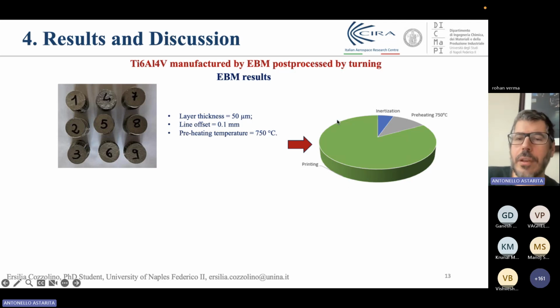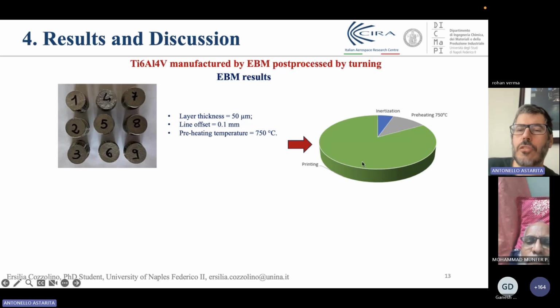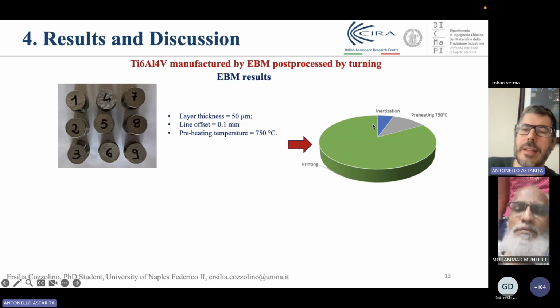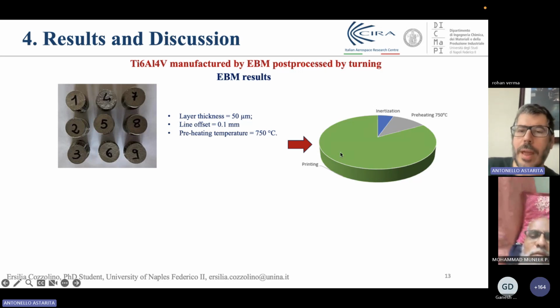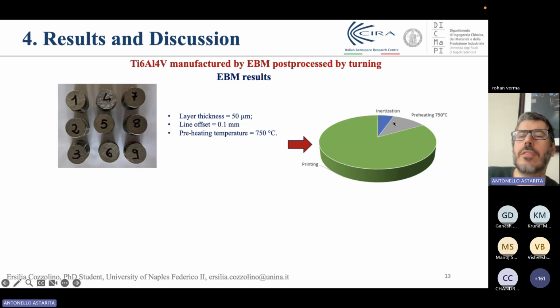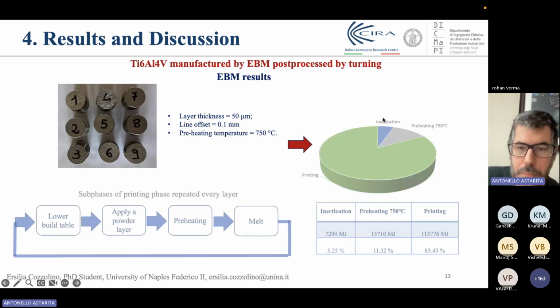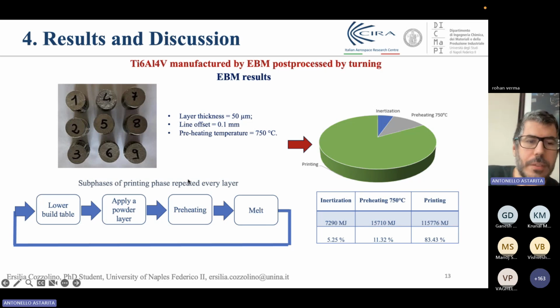In this pie chart, you can see the use of energy for the different stages of the process. You can see that most of the energy, of course, is required for the printing, but you have a non-negligible part of energy that is due to the preheating of the whole job, and another non-negligible part that is related to inertization. Okay. So this is, let me say, the flow chart of the process, and we measured the amount of energy required for each step.